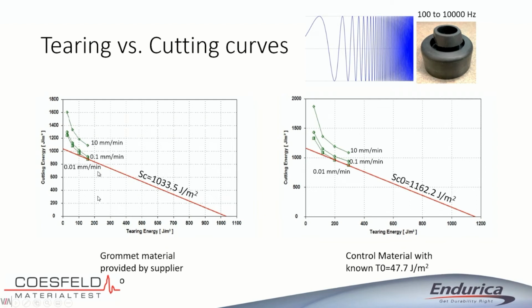Now, what we're interested in then is the total of the cutting plus the tearing. So I've plotted a red line here. That red line is basically the line along which the sum of the cutting plus the tearing energy is equal to the minimum observed total sum of energies, right? So we're trying to minimize that, and that total energy is minimized basically at the point on the lowest rate curve that just barely touches the red line.